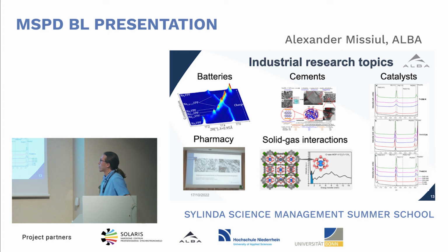And of course, we work with catalysts. The catalytic reaction itself does not change that much. We expect that catalysts should not change during catalytic reaction, so we should not see much difference. But for modern catalysts, there is also an activation process. This activation process of the catalyst includes chemical change, and we can see these changes. For example, here, a mixed platinum-palladium catalyst was investigated, and it appears that during its activation, it first oxidizes to corresponding oxides and then reduces back to the metals. And only after that, the catalyst starts working.